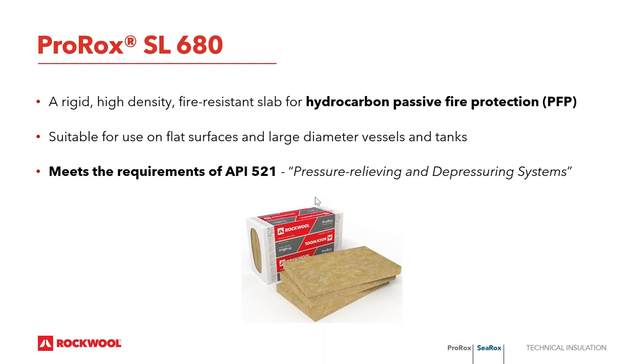This is also a common fire standard, but it's more frequently common for large diameter tanks. Within API 521, there is a requirement that the material must function effectively up to, I think it's 1660 degrees Fahrenheit, with an exposure for 2 hours. The SL680 is a very similar product, with almost identical thermal and physical properties in a flat board form, to that new product I talked about, the PS680, our mandrel wound pipe insulation. It's very similar based on the ingredients and properties such as density and chemical makeup. So this is suitable for hydrocarbon fire protection on flat surfaces, like large diameter vessels and tanks.